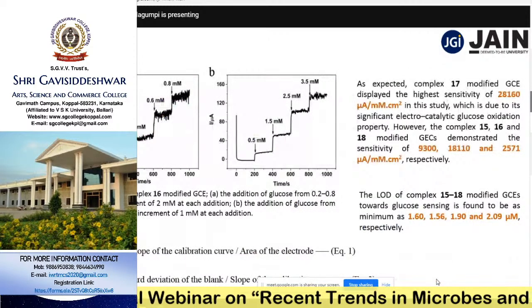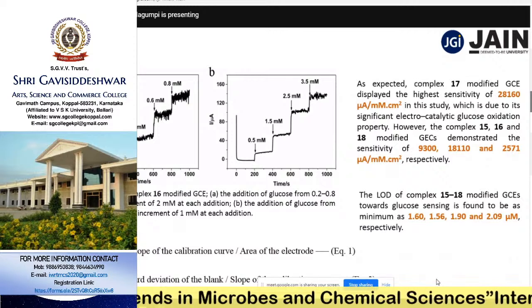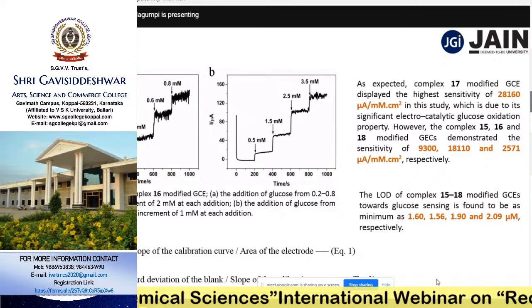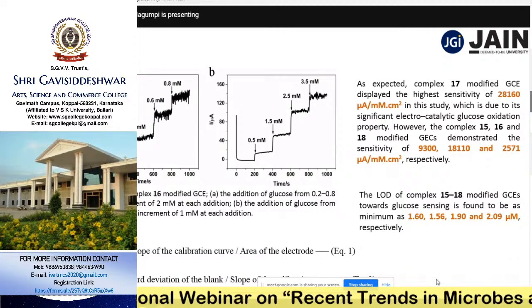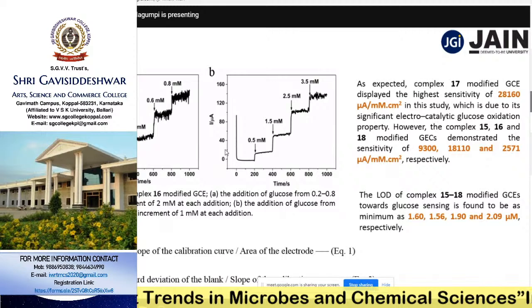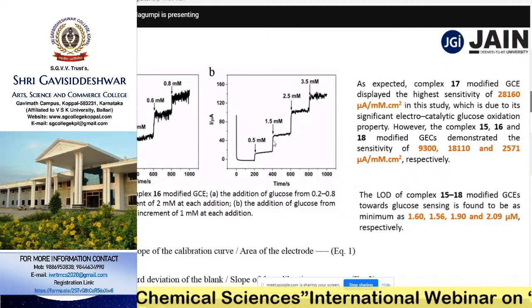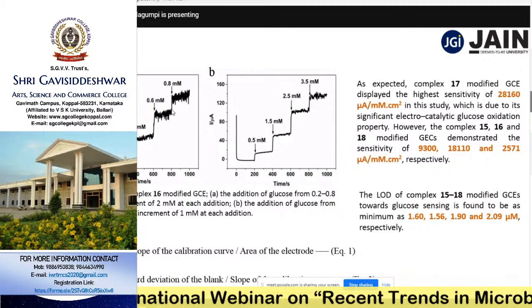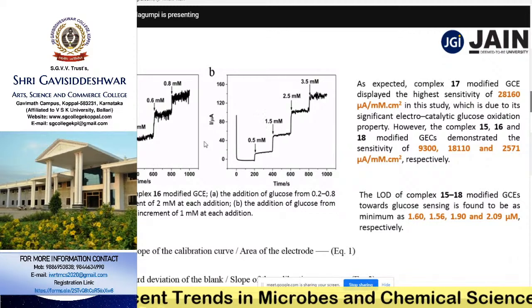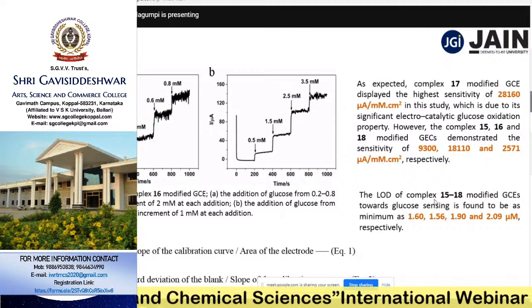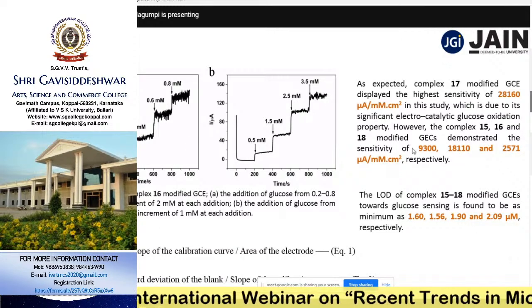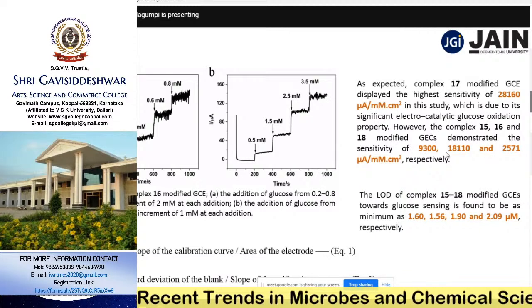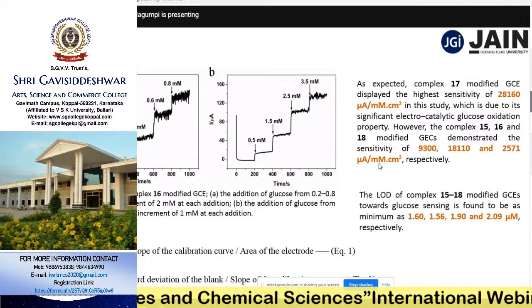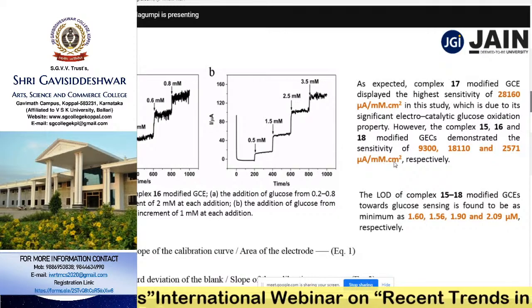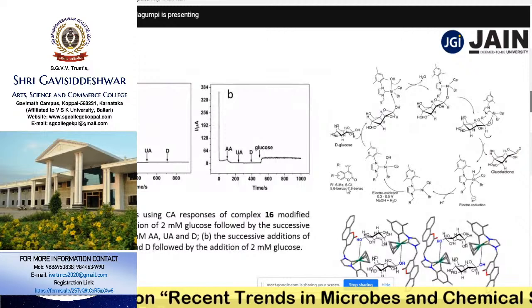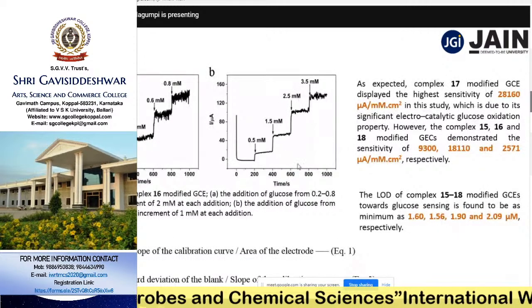So these activities emphasize that the complexes can be used as glucose sensors, that too non-enzymatic glucose sensors. Further, we have studied the calibration plot, sensitivity of the electrodes, and the limit of detection of glucose using chronoamperometric techniques. The chronoamperometric technique is a time-dependent addition of glucose into the electrocatalytic cell with increasing glucose concentration. With the help of these techniques, one can easily identify the sensitivity of the electrodes, which is quite high. All these electrode materials have shown high sensitivity in the range of 9,000 to 28,000 microamps per millimole of glucose per centimeter square. With the help of this, one can easily identify the unknown concentration of glucose present in a blood sample.